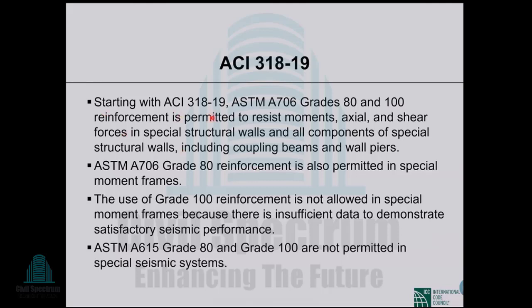Starting with ACI 318-19, ASTM A706 grades 80 and 100 reinforcement is permitted to resist moments, axial and shear forces in special structural walls and all components of special structural walls, including coupling beams and wall piers. So for special structural walls, ACI 318-19 allows you to use grade 80 and even grade 100, which is produced according to ASTM A706. ASTM A706 grade 80 reinforcement is also permitted in special moment frames.